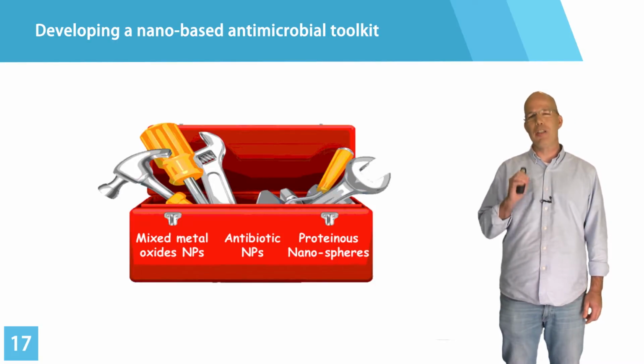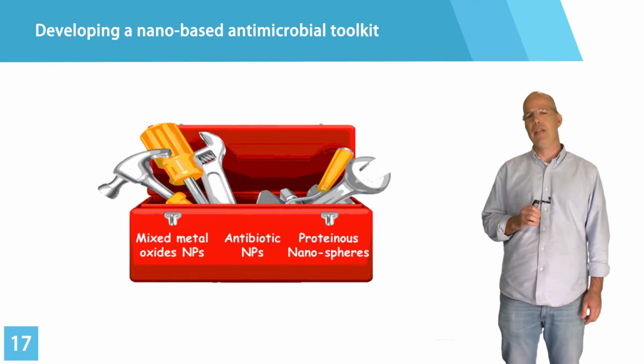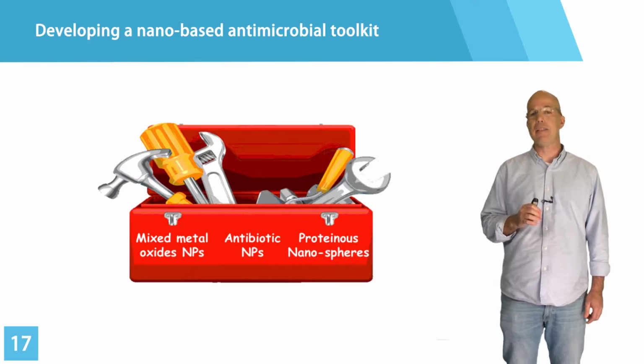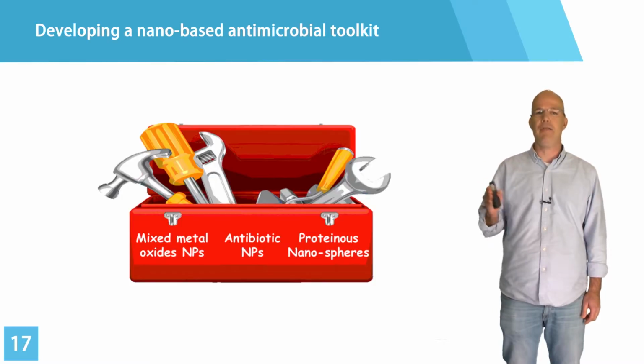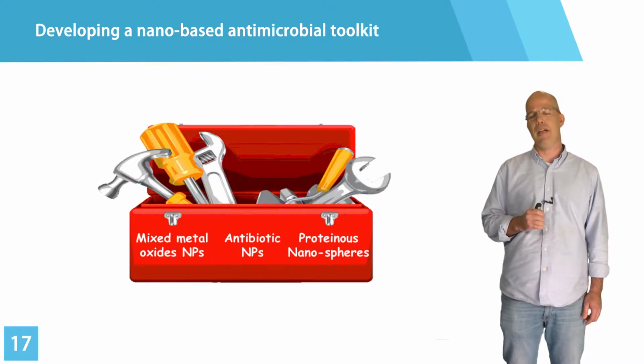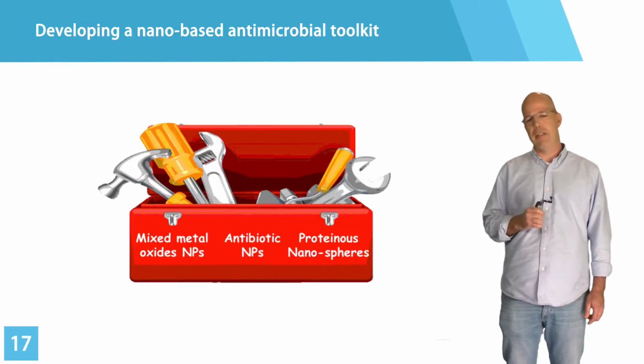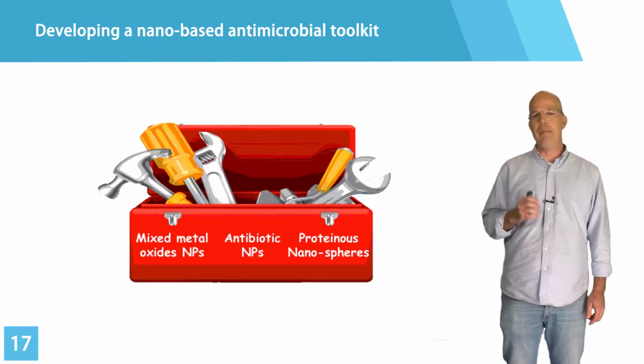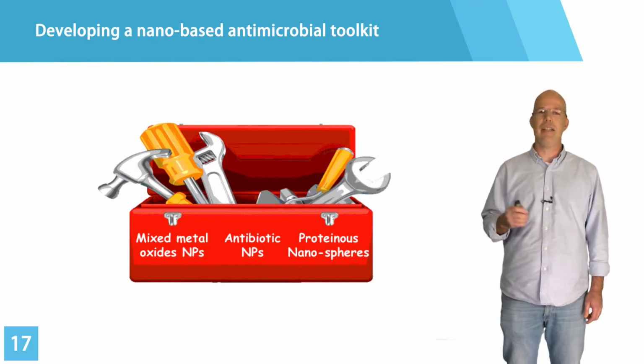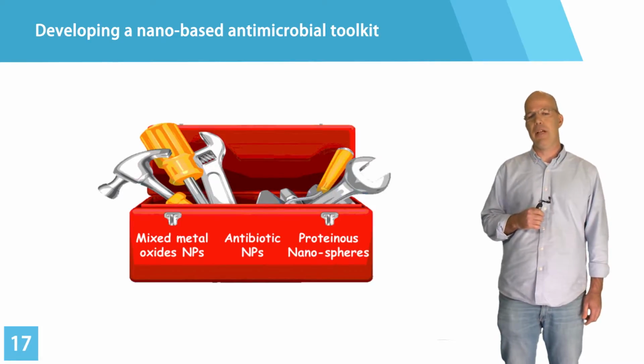One will use novel metal oxides, which are highly potent antimicrobial agents, but making nanoparticles out of them will make them even more active. The other is taking commercially available antibiotics, the ones that people have been using and that are losing their activity against bacteria. What we're offering is to make nanoparticles out of them and restore their activity. The last one is taking proteins and making them into nanoparticle spheres, basically making a cargo that will carry antimicrobial agents at higher payloads and will also damage the cell and have antibiotic activity.